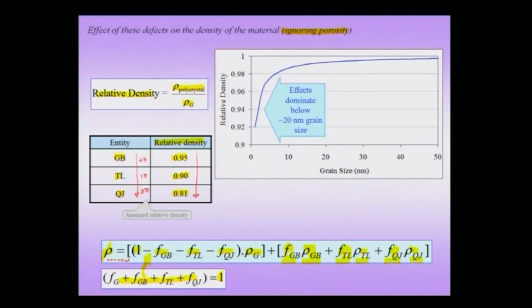Now, if I plot this relative density using these values for the grain boundary, triple line and quadruple junction, I notice that the relative density actually decreases with decreasing grain size, and you see that below about 20 nanometers, this effect tends to dominate. So, when I am below about 20 nanometers, I have to worry about the presence of grain boundaries and triple lines in the calculation of relative density.